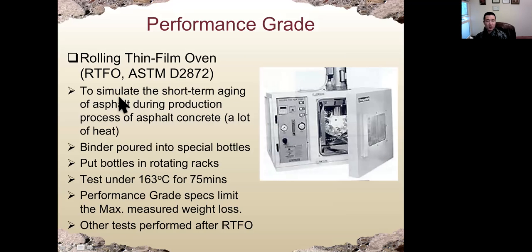This test is to simulate the short-term aging process of asphalt during the production period. In the production period, we heat up the asphalt and mix the asphalt binder with sand and coarse aggregate, and then we pave the road. We do that on the first day of construction. This rolling thin film oven test simulates that first day, the short-term aging process. Why do we care about the first day? Because during the production period, we increase the temperature of the asphalt binder, and during that process, we have a lot of heat due to the high temperature.